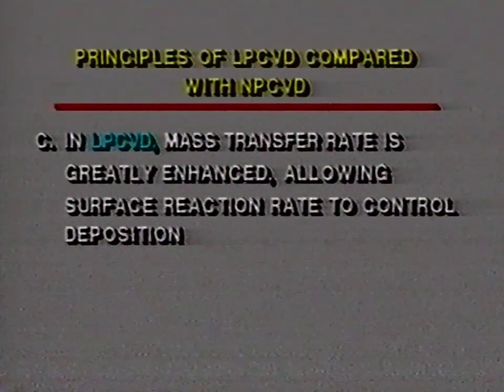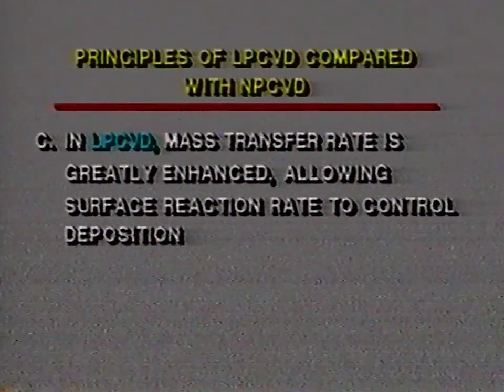In LPCVD, which is shown here, the mass transfer rate is greatly enhanced, allowing the surface reaction rate to control the deposition. Now, vertical closed-space substrates are uniformly coated as a result, but it still perhaps isn't clear why.